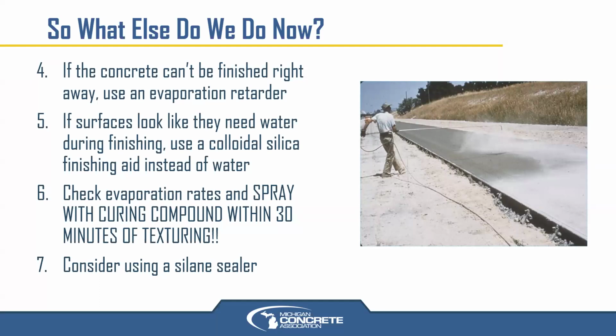Well, that's the next bullet point, which is if you look like you need water during finishing and you don't want to add water because you're concerned about shrinkage, you're concerned about permeability, water cement ratios, you're concerned about potential for scaling, we recommend using a colloidal silica finishing aid instead of water. So a non-water product to be used in the finishing operations, such as a colloidal silica. There's a lot of different proprietary products out there.